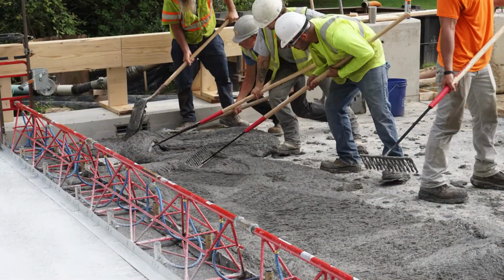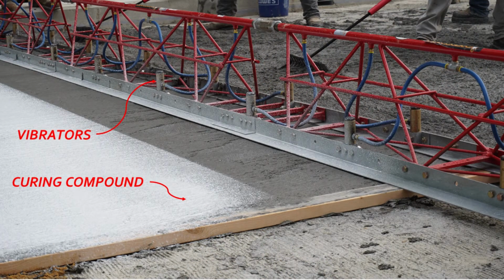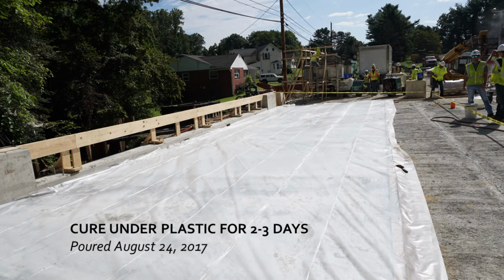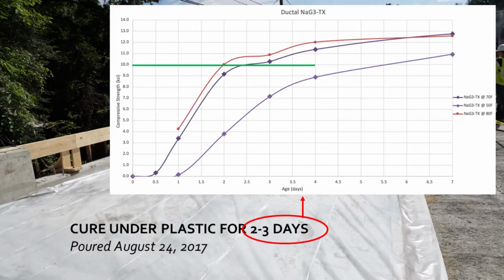So again, spread it out with some rakes in front of the screed, and then we hit it with a heavy dose of curing compound after the screed has passed over. The screed has high energy input to really consolidate the material as it passes over it, and then we cover it with plastic for curing. We don't have to wet cure it. We just want to seal in the moisture that is already in the mix itself, and let it cure for about 2 to 3 days.